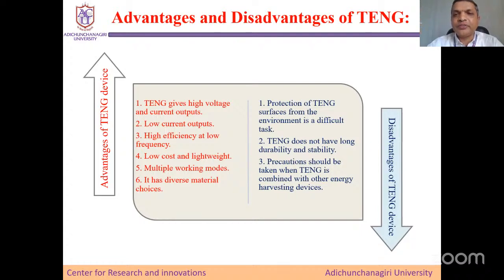But at the same time, there are some limitations, such as protection of the TENG surface from the environment is very difficult, because all the triboelectric nanogenerators require surface texture. Whatever potential or electricity you generate is directly proportional to the texture of the material on the surface. So it is very difficult to maintain the structure because of the tribo effect. TENG does not have long durability and stability. This is another thing we are finding, because after 300 or 400 cycles, the TENG capacity reduces. And precautions should be taken when TENG is combined with other energy harvesting devices.